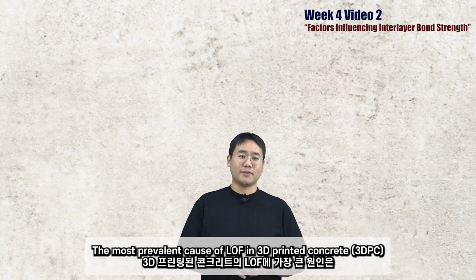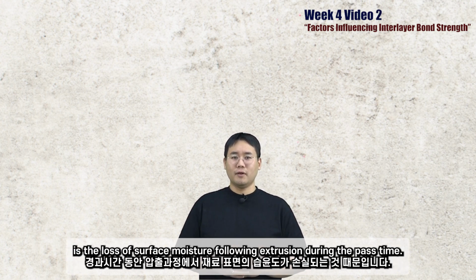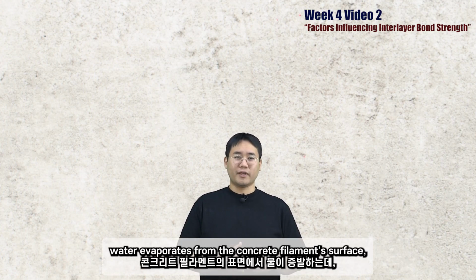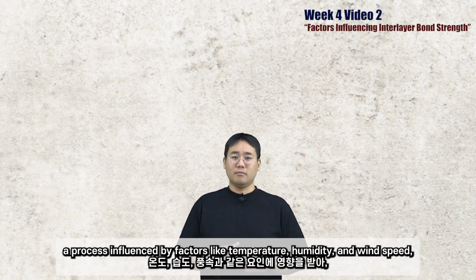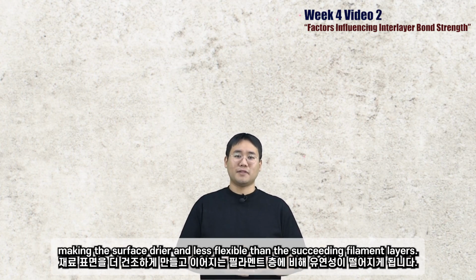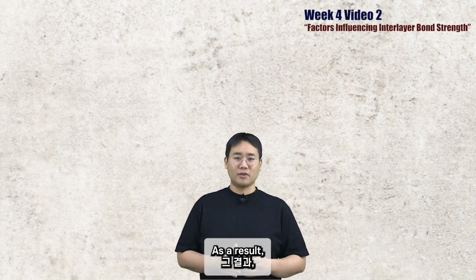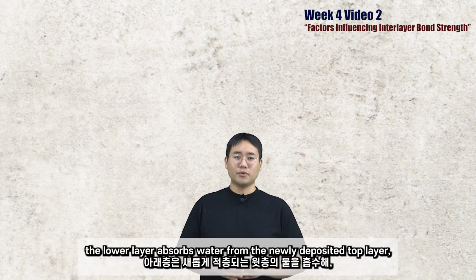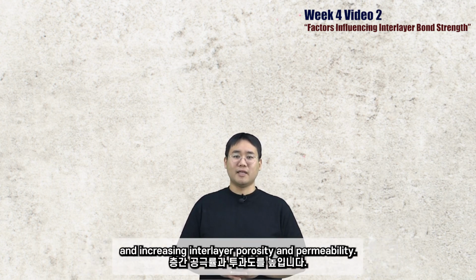The most prevalent cause of lack of fusion in 3D printed concrete is a loss of surface moisture following extrusion during the pass time. After extrusion, water evaporates from the concrete filament surface, a process influenced by factors like temperature, humidity, and wind speed, making the surface drier and less flexible than the succeeding filament layers. As a result, the lower layer absorbs water from the newly deposited top layer, expelling air into the layers and increasing interlayer porosity and permeability.